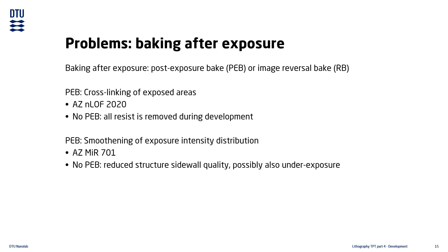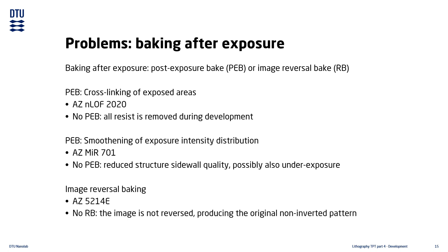Finally, some resists are capable of changing between positive tone and negative tone by baking after the exposure. This is called an image reversal bake — an example is AZ-52-14E. Forgetting the reversal bake means that the exposed pattern will not be inverted. The development will still work, but the result will be the original non-inverted pattern.